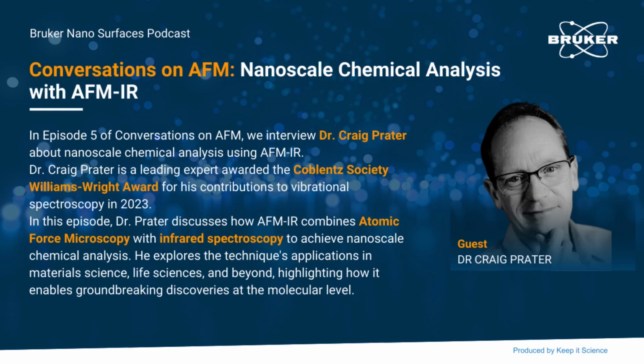And so the big advantage of AFM-IR was that it was able to provide a measurement of infrared absorption with a spatial resolution not limited by the wavelength of the infrared light, but rather by the size of the AFM tip. Basically enabling spatial resolution to go down to the scale of 10 to 20 nanometers, in some cases smaller than 10 nanometers. Which is what we all love. We all love good resolution, absolutely.